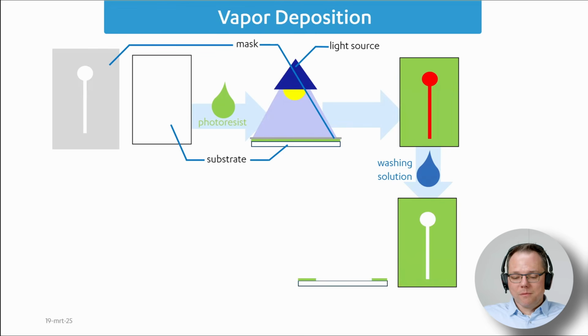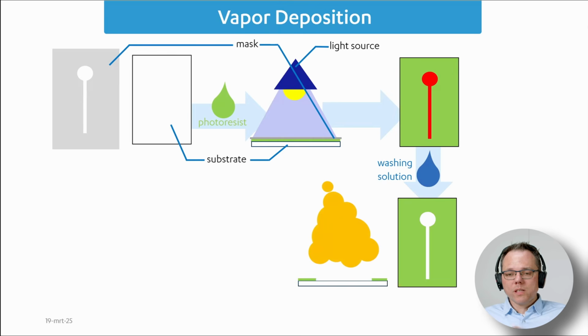Now we have basically our mask on our substrate, and we expose this mask to a metal vapor. We can do this, for example, by putting the substrate and a metal source into a vacuum, and then heating up that metal source. A popular way of doing it is sputtering. So we're shooting ions or other particles at the gold so that it starts to heat up and go into a gaseous form, and then because the substrate is colder, it deposits on the substrate.